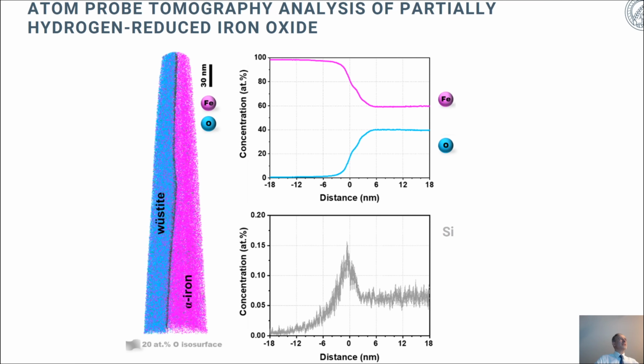And now we switch gears and go to a much finer scale, namely to atom probe analysis. And you see here a direct atomic scale resolved interface between the wüstite on the left-hand side and the alpha iron on the right-hand side. And you can very nicely see this very strong drop in the oxygen content, as we have stipulated before, which explains how the oxygen must, through this chemical potential gradient, now diffuse outbound through the iron.